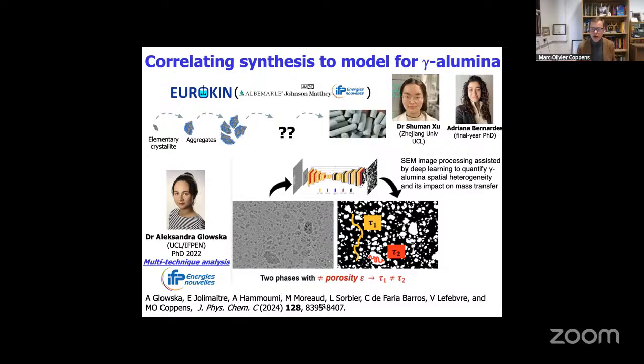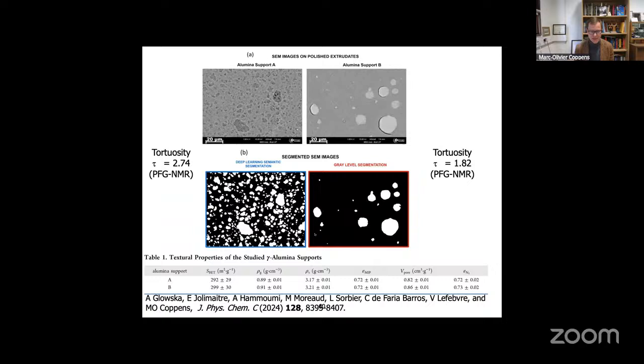Only that gives you an idea. It's like that image of the elephant and the parable of the blind people touching the trunk, or the legs, or the hair, and thinking it's this shape or it's that shape. You need a variety of techniques. And so we found indeed that different alumina supports have entirely different structures. They may have different tortuosities. And even if they have similar local porosities overall, as you see in this data below, still the overall diffusion properties may be different.